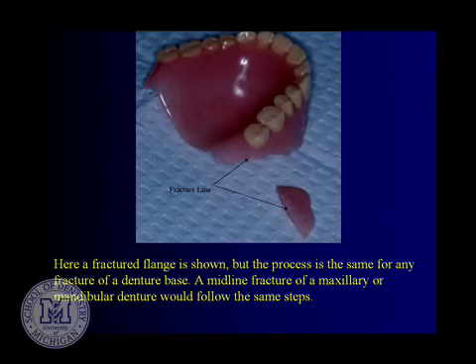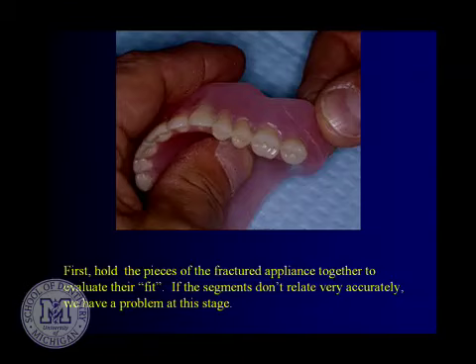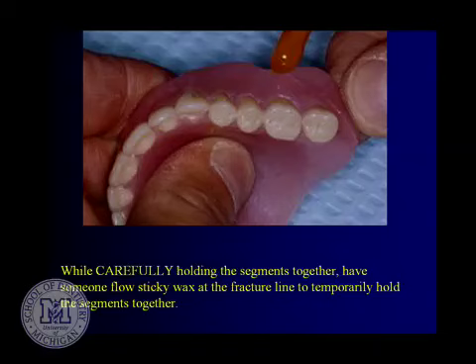Sometimes you have to go to plan B, C, or D. The hope is when the patient comes in it's been broken but they haven't tried to fix it with superglue. If you take literally one drop of the real runny superglue and put it on one of the mating surfaces, holding the two pieces together for about 10 seconds, it will weld them together. But that's not your repair—that's just to tack things together, like sticky wax.